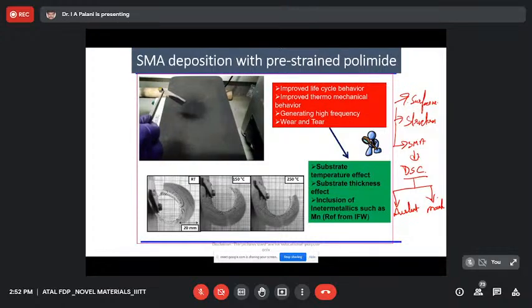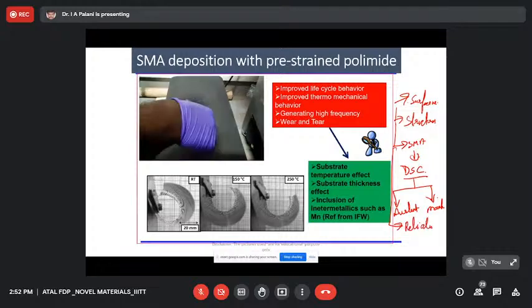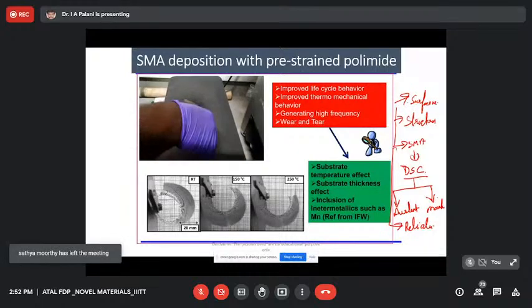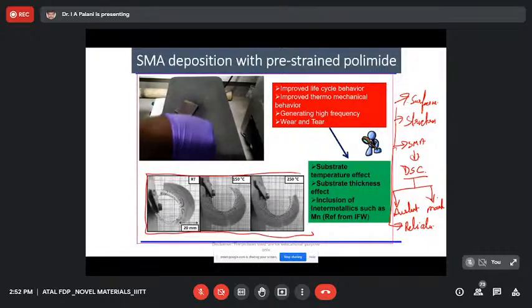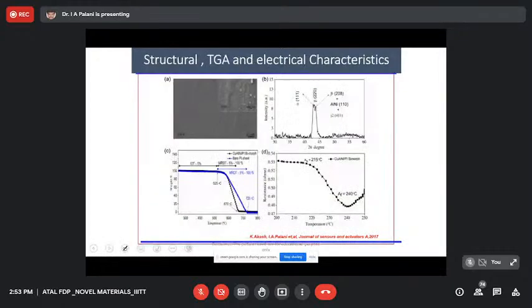And in order to study the actuation behavior, the option available with us is a reliability test setup. We have developed a small reliability test setup basically to understand the behavior of this shape memory alloy actuation. This image is taken from our laboratory, where initially this is the shape memory alloy Bimorph at room temperature, clamped to a plate. When you heat the plate, there is actuation at something around 150 degrees Celsius. You can see an opening up of the shape memory alloy, and at 250 degrees Celsius, there is further elongation.